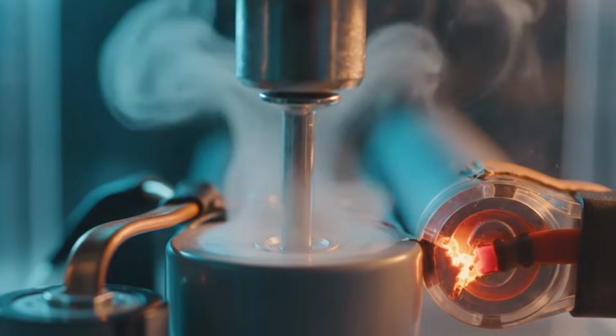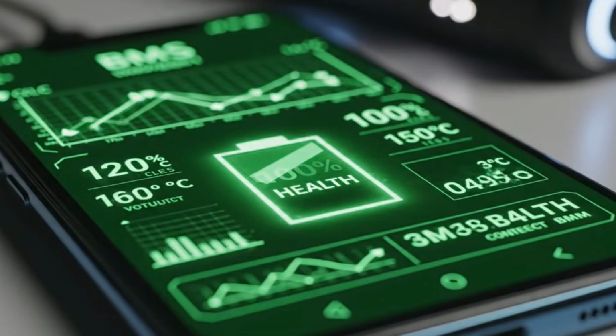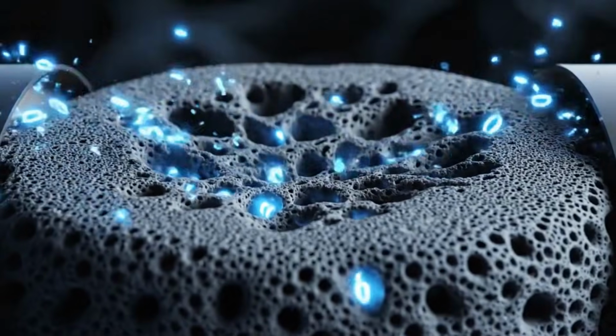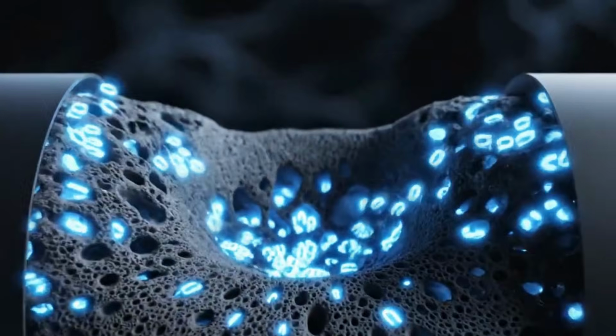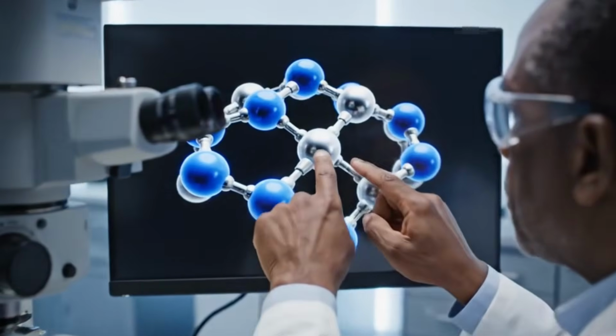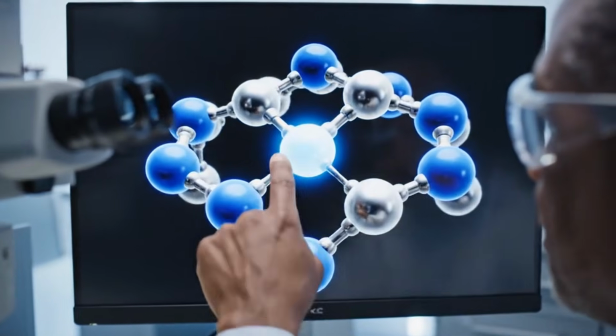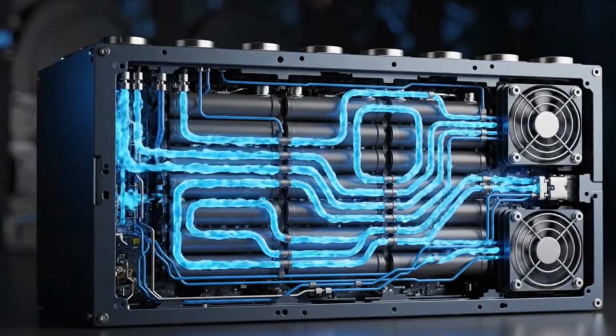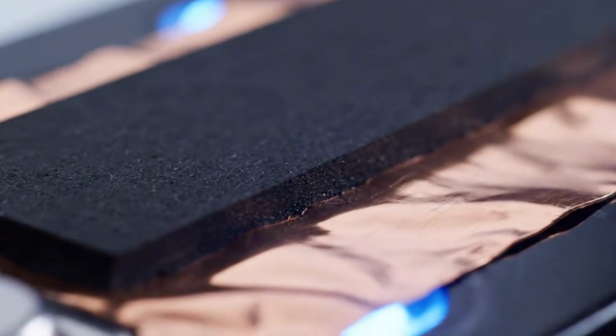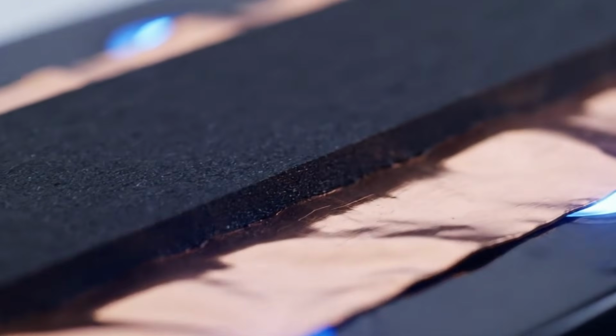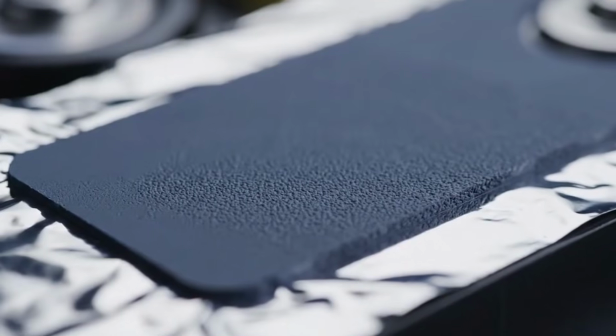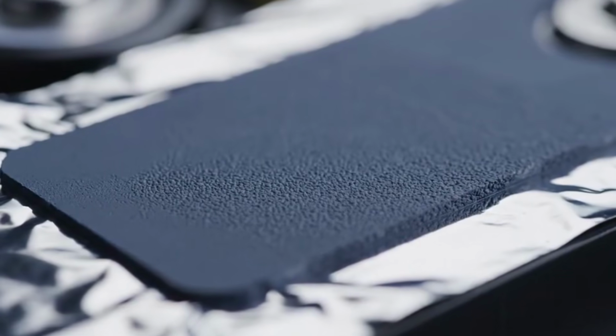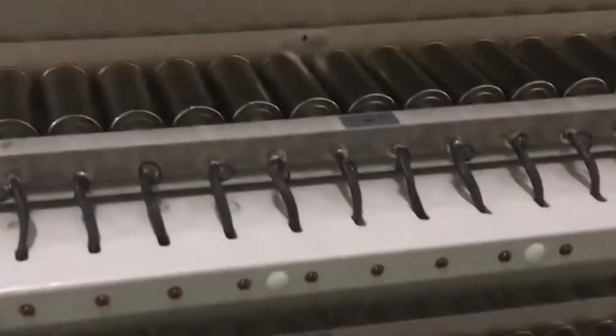Manufacturing is the bigger part of the story. The electrode coating process is where the production magic really happens. You take your cathode or anode material, grind it into a fine powder, mix it with a binder and a solvent to create a thick slurry, and then coat that slurry onto a roll of aluminum or copper foil using something that looks like an industrial printing press. The foil runs through at speed, the slurry gets laid down in an even layer, and then it passes through a long drying oven that evaporates the solvent and leaves behind a solid electrode coating.